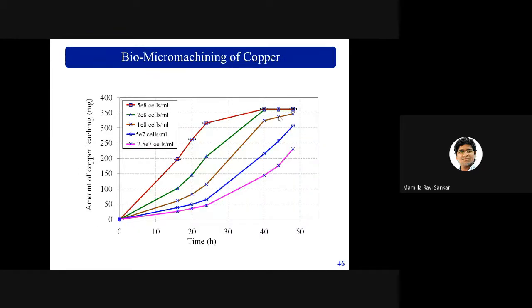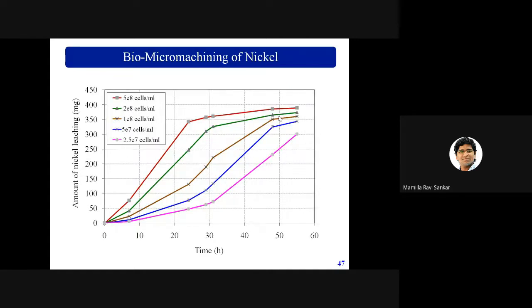Now we can see the amount of leaching with respect to time. Where we are using the cell density, for example, 2.5 e power 7 to 5 e power 8 cells per ml. As your number of cells increases, automatically you can increase the material removal rate. We have done this for multiple materials: copper, nickel, and even aluminum. The mechanism is approximately the same, and as the number of organisms increases, the material removal increases automatically.